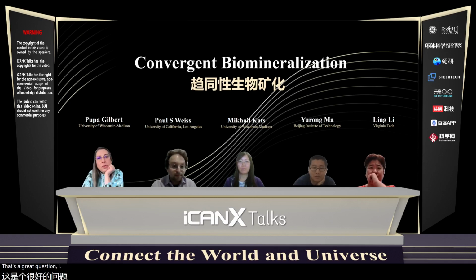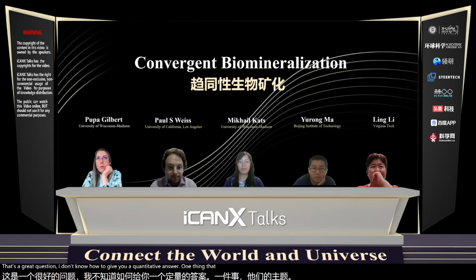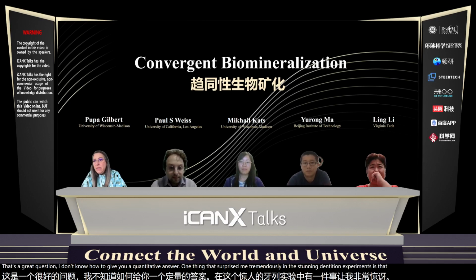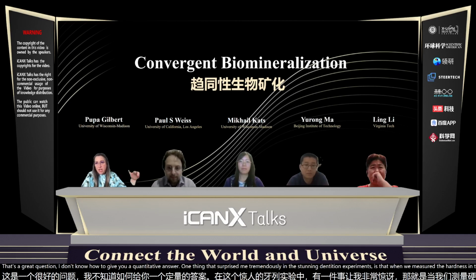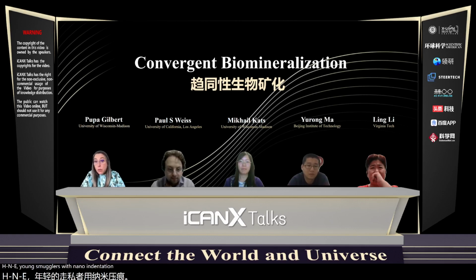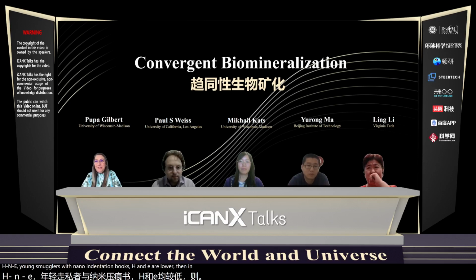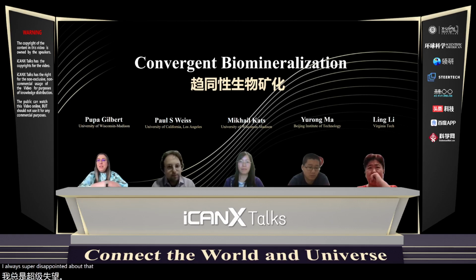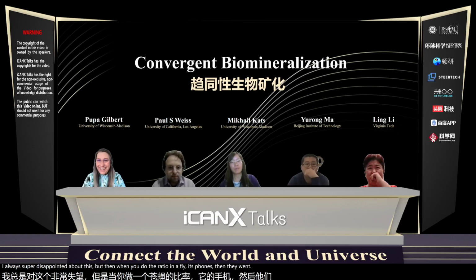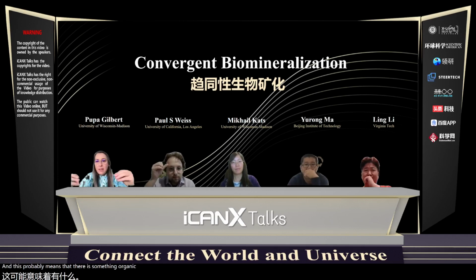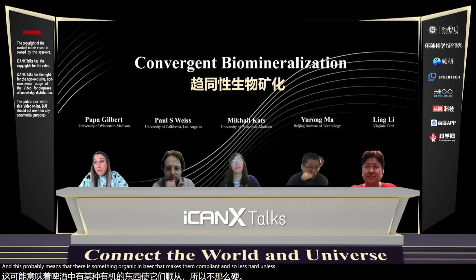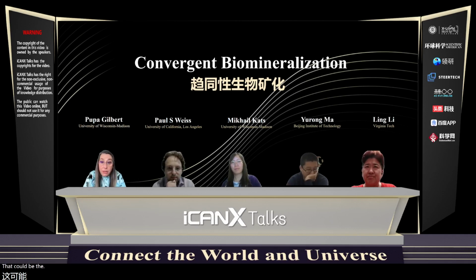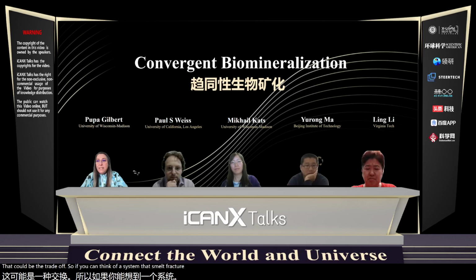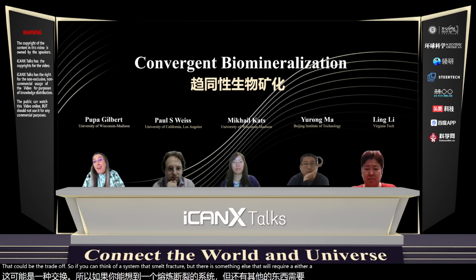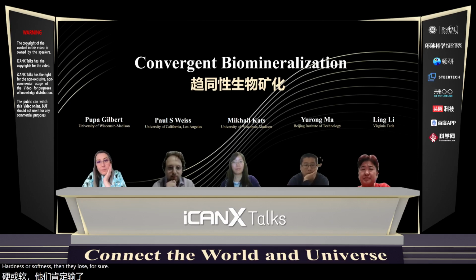That's a great question. I don't know how to give you a quantitative answer. One thing that surprised me tremendously in these nano-indentation experiments is that when we measured the hardness and the stiffness, so H and E, Young's modulus, with nano-indentation, both H and E are lower than in the geologic single crystals. I was super disappointed about this. But then when you do the ratio and apply exponents, then they win. And that probably means that there's something organic in there that makes them compliant and so less hard and less stiff. Therefore, that could be the trade-off. So if you can think of a system that's not fracture, but something else that will require either hardness or stiffness, then they lose for sure. So I guess that's the most quantitative answer I can give you.